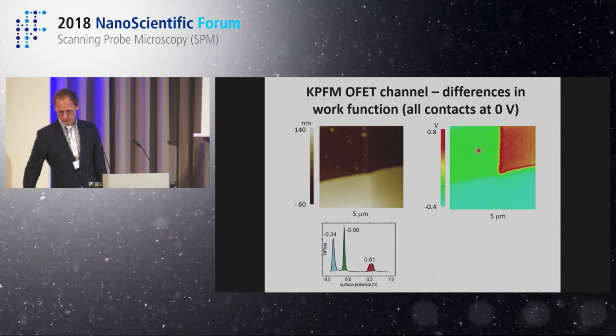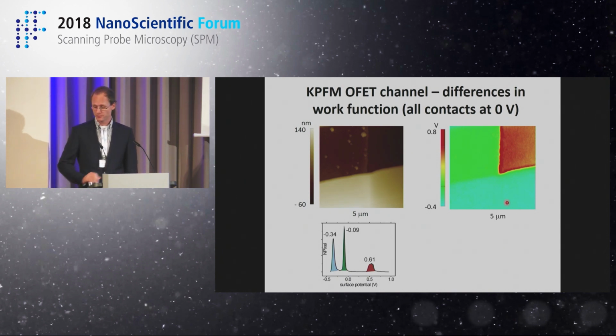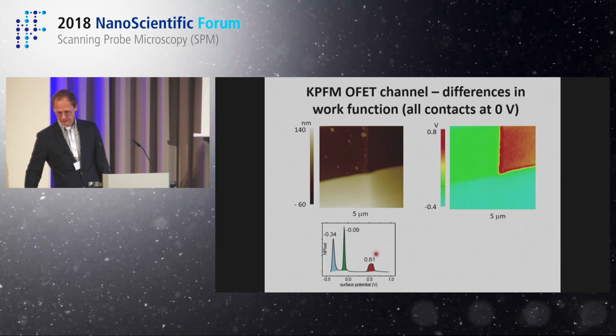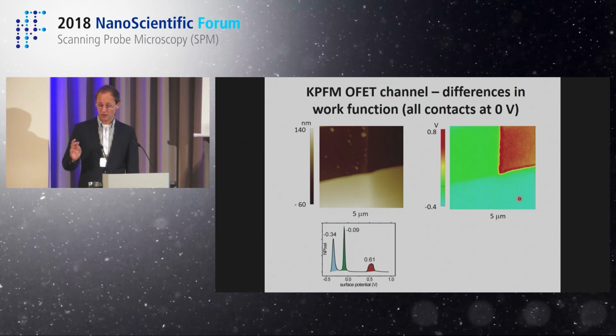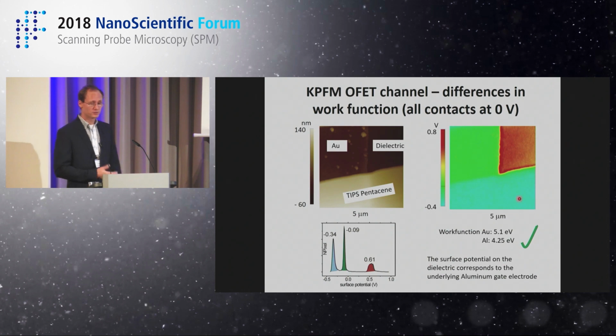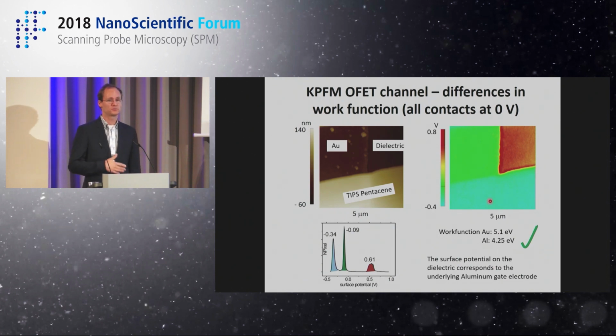You can look at gold, so our metal contacts here are of gold, and the gate contact below is made of aluminum, and you can see that there is a potential difference that basically corresponds to the difference in work functions between these two materials. Then you have here an additional value that corresponds to, let's say, the Fermi level of your semiconductor. All this is very important and relevant information for a lot of semiconductor device-related aspects. For example, differences in work function are a problem when you want to inject carriers from one material to another. So you have to think about them. So just this measurement contains a lot of information in order to improve devices and understand what's happening.